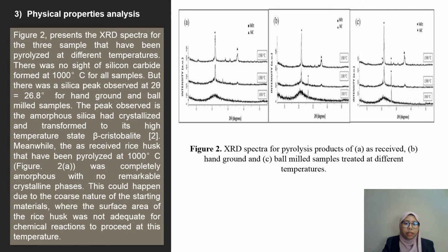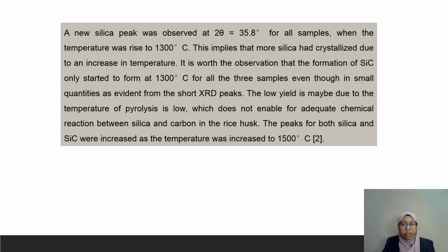Meanwhile, the as-received rice husk that had been pyrolyzed at 1000 degrees Celsius was completely amorphous with no remarkable crystalline phase. This could happen due to the coarse nature of the starting material, where the surface area of the rice husk was not adequate for a chemical reaction to occur at this temperature. A new silica peak was observed at 2θ equal to 35.8 degrees for all samples when the temperature was raised to 1300 degrees Celsius.